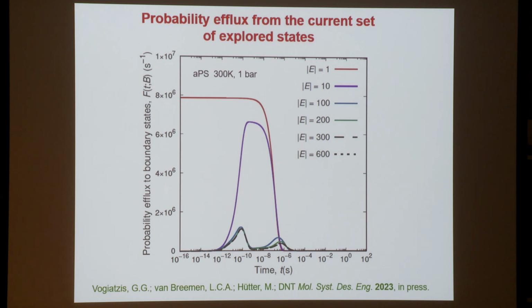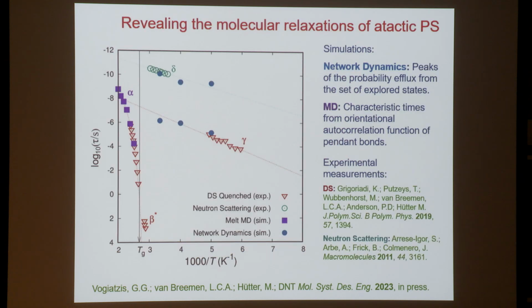So these are characteristic times that one can bring into a logarithm of relaxation time versus inverse temperature plot. And here they are. These cyan points are the characteristic times from the calculation we showed earlier. If we repeat the calculation at different temperatures, for example, 250 or 200 Kelvin, we see these characteristic times. And it is obvious that these times are representative of some molecular processes happening inside the glassy polymer.